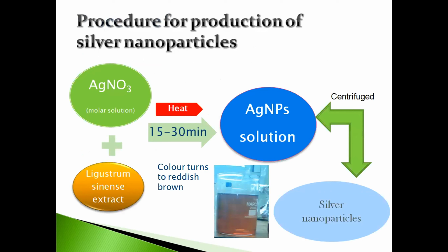So the procedure of production of nanoparticles that I used was to prepare a silver nitrate solution, whatever kind of molarity you want. If you want to prepare a 1 millimolar solution or a 10 millimolar solution, you add this amount of silver nitrate in distilled water according to the molarity of the solution.